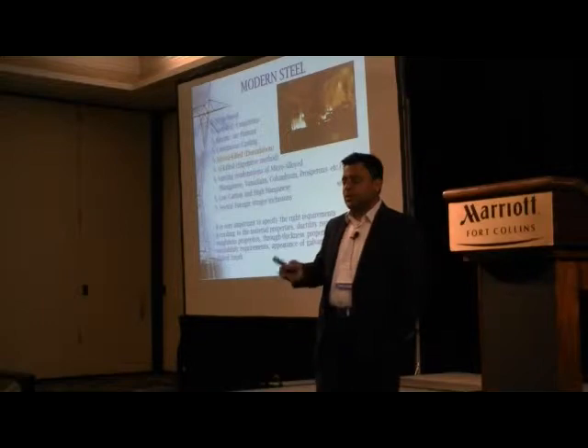So now they have scrap-based steel, as roll conditions, electric arc furnace, which is quicker and faster, continuous casting. Again, all these things are for their supply and demand. And the most important thing I put in red is silicon killed, which is very critical. For poles we have certain guidelines, but for lattice there are no guidelines. So silicon killed is most common for lattice angle. Aluminum killed is much less common because it's more expensive for them.